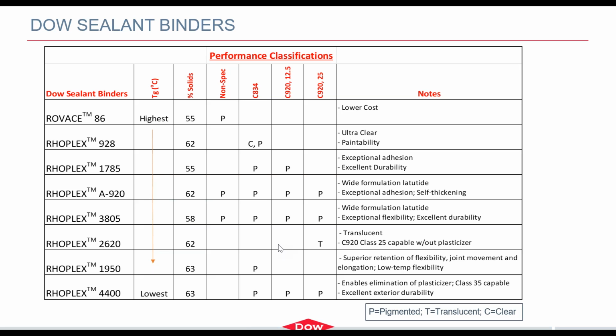This is an indication of which polymers can be used for different performance requirements. So if a customer comes to me and says, I'm looking for a polymer that can just fill a joint, and I'm looking for low cost, most likely I will recommend Rovace 86. If they want to formulate without plasticizer in the formulation, and I will get into this much deeper when I talk about Rhoplex 4400 later, then I would recommend either Rhoplex 1950 or Rhoplex 4400. As we dig into the details, I can maybe get that down to one option, or they might like to look at two options. And Rhoplex 4400, while it does meet the ASTM C920 Class 25 specification, is also capable of meeting Class 35 as well.